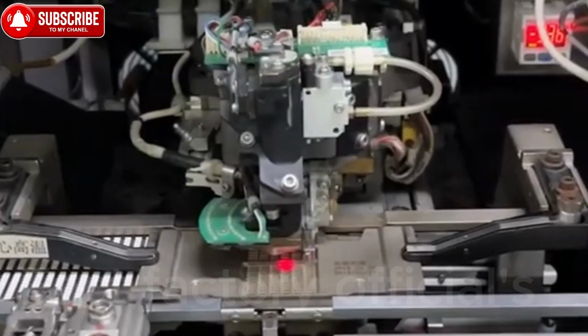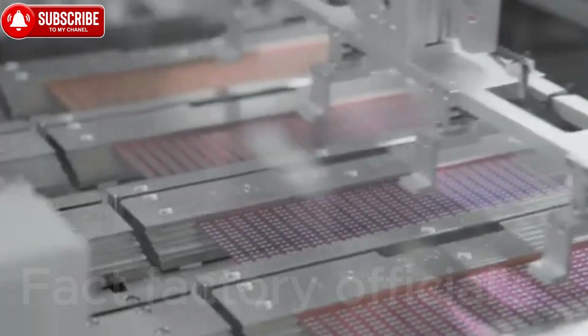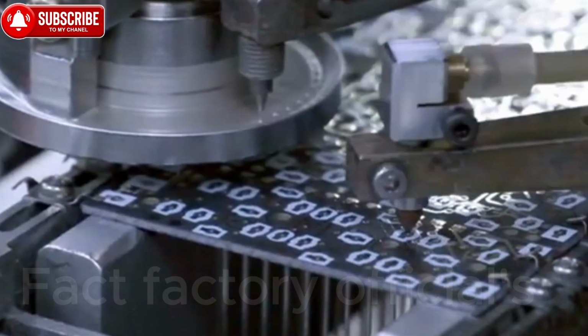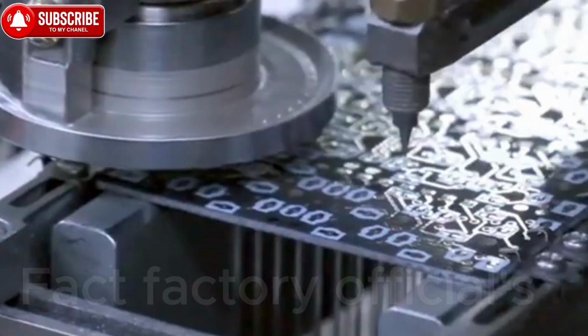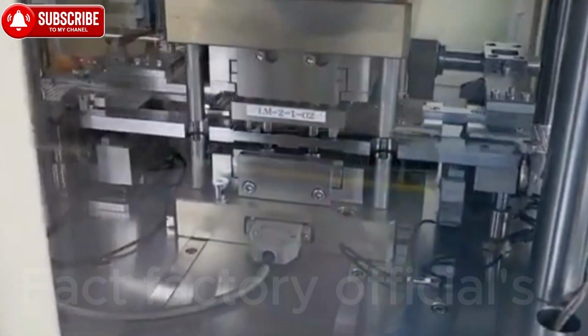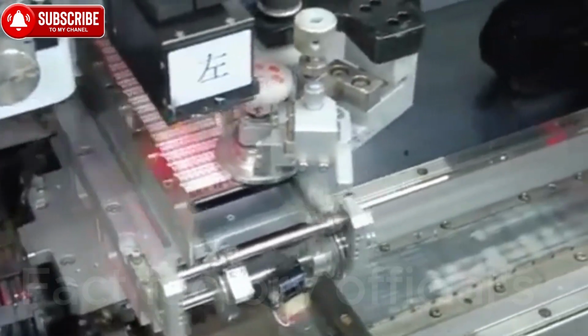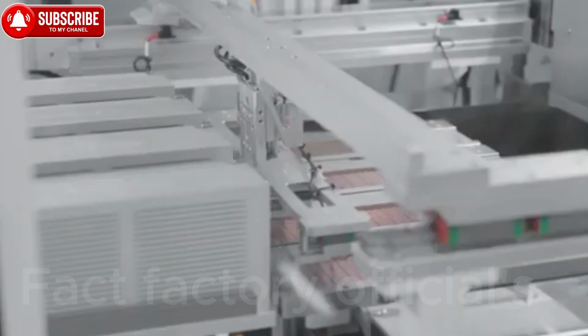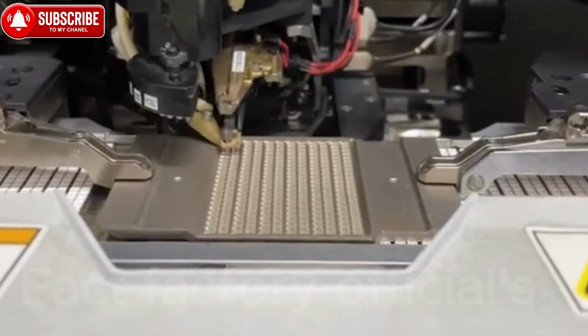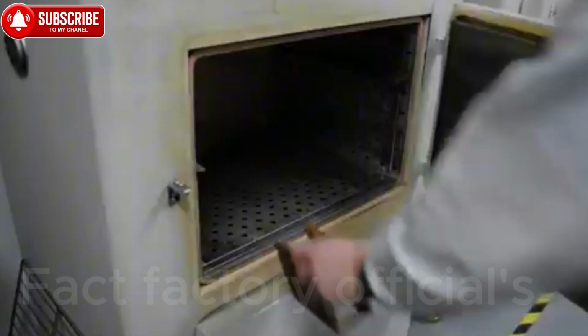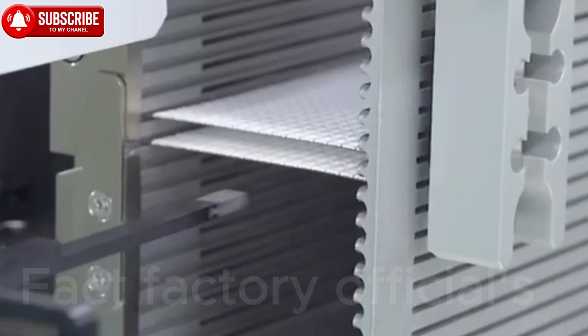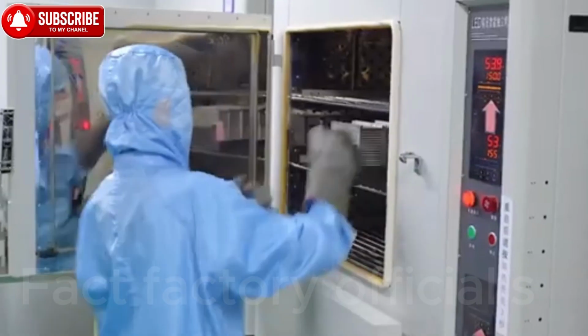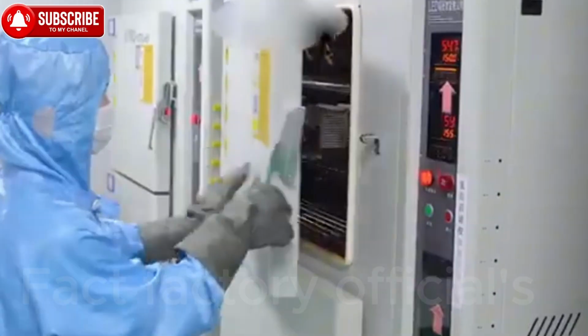Precision wire bonding. After the LED chip has been fully secured onto the metal lead frame, the LED tray is transferred to an automated wire bonding machine. A spool of 99% pure gold wire with a diameter of 18 to 25 micrometers, 3 to 5 times thinner than a human hair, is fed into the system. High-resolution industrial cameras scan each individual chip and its corresponding lead terminals, calculating their exact positions with accuracy down to just a few micrometers. Using a combination of heat and ultrasonic energy, the machine forms a tiny gold ball at the tip of the wire.